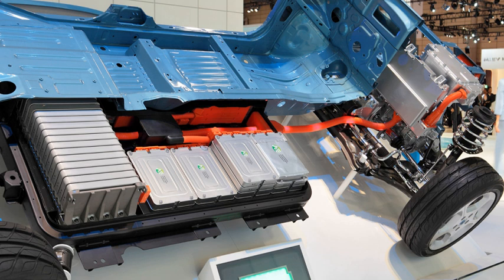Lithium-ion batteries, widely known via their use in laptops and consumer electronics, dominate the most recent group of EVs in development. The traditional lithium-ion chemistry involves a lithium cobalt oxide cathode and a graphite anode, yielding cells with 200-plus watt-hours per kilogram specific energy, good specific power, and 80–90% charge-discharge efficiency. The downsides include short cycle lives and significant degradation with age. The cathode is also somewhat toxic, and traditional lithium-ion batteries can pose a fire safety risk if punctured or charged improperly. These cells don't accept or supply charge when cold, so heaters can be necessary in some climates.